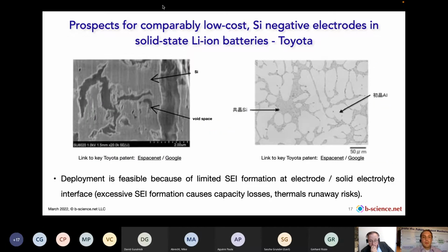So if we look at the silicon ones and what Toyota is patenting, it's interesting to see how they produce porous silicon structures that might have quite a high surface area that with liquid electrolytes would cause probably too many side reactions. But with a sulfide electrolyte, it seems there are not too many interface reactions, and the volume expansion of the silicon can be accommodated by having this void volume, although it should be filled with electrolyte, but it's a way of distributing the volume change and avoiding crack formation.